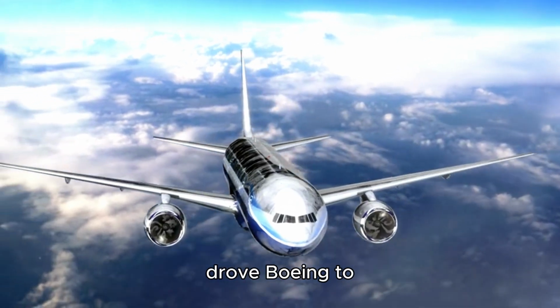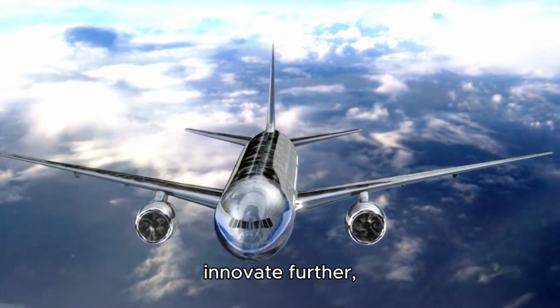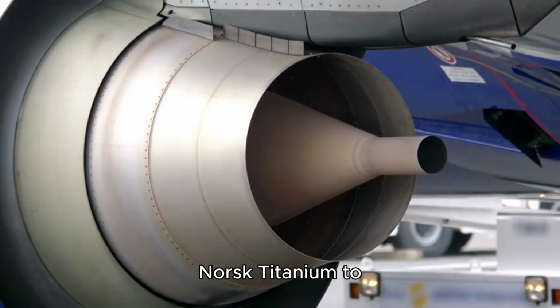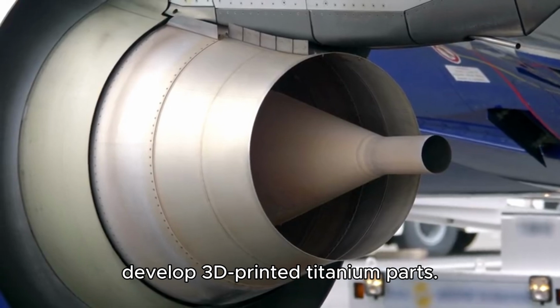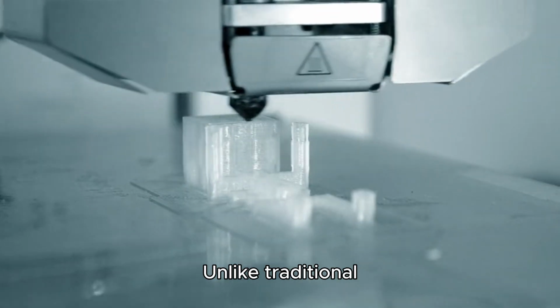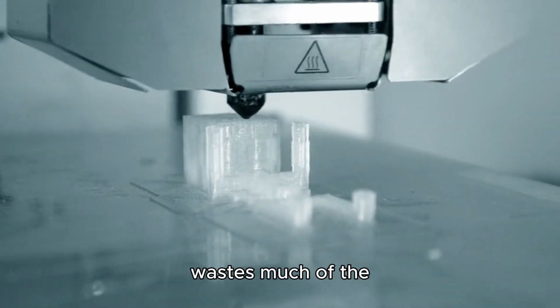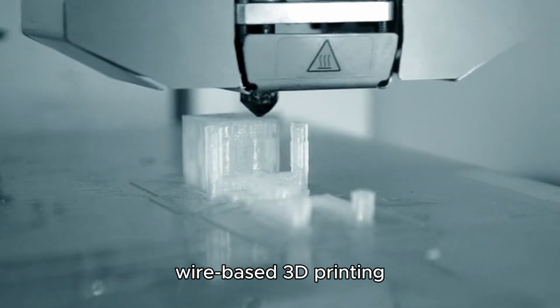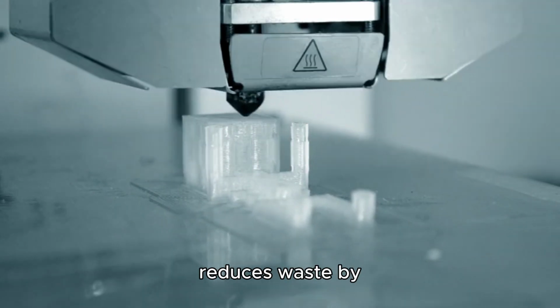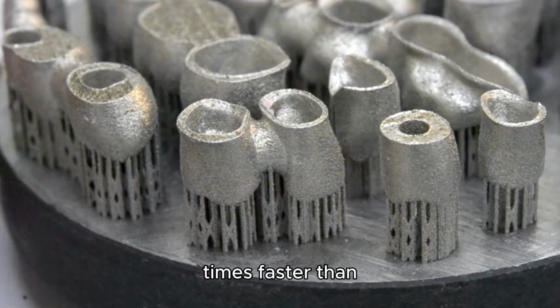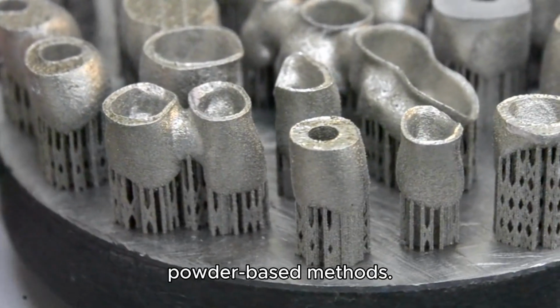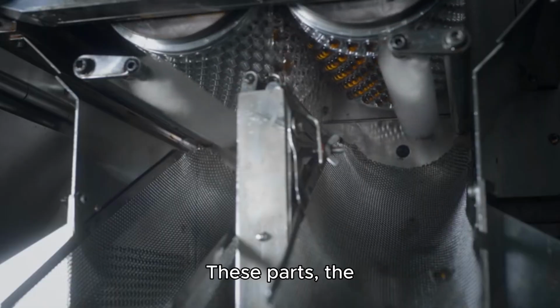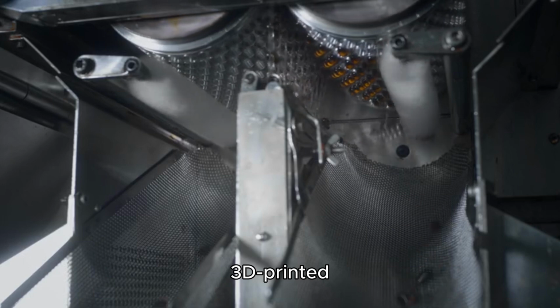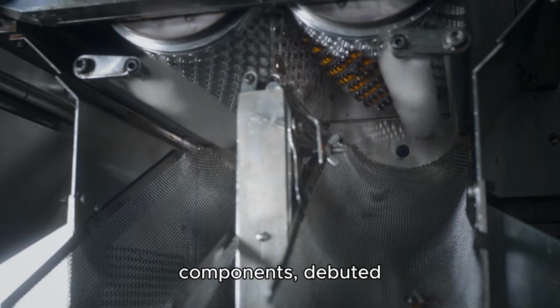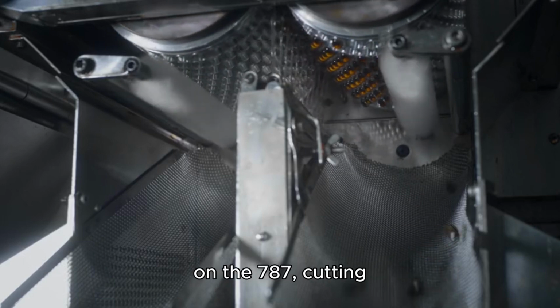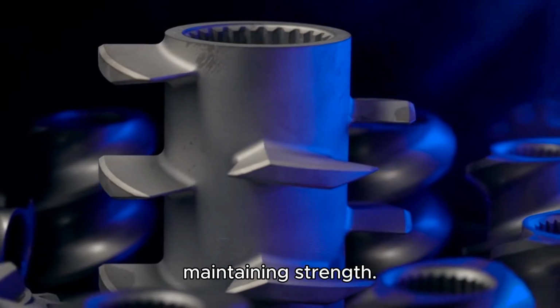Titanium's high cost drove Boeing to innovate further, collaborating with Norsk Titanium to develop 3D printed titanium parts. Unlike traditional machining, which wastes much of the material, Norsk's wire-based 3D printing reduces waste by 25 to 50%, and is 50 to 100 times faster than powder-based methods. These parts, the first FAA-certified 3D printed structural components, debuted on the 787, cutting costs while maintaining strength.